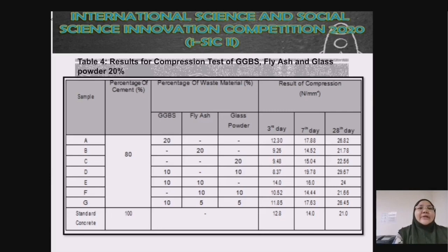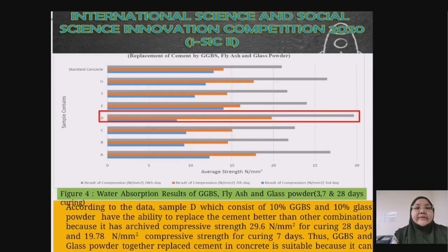This table shows the compression test of the sample of GGBS, fly ash and glass powder. From the result in the graph, according to the data, sample D, which consists of 10% of GGBS and 10% of glass powder, has the ability to replace the cement better than another combination because it has achieved compressive strength 29.6 Newton per mm square for curing 28 days and 19.78 Newton per mm square compressive strength for curing 7 days. Thus, GGBS and glass powder together replacing cement in concrete is suitable.